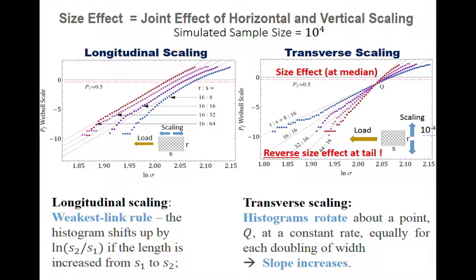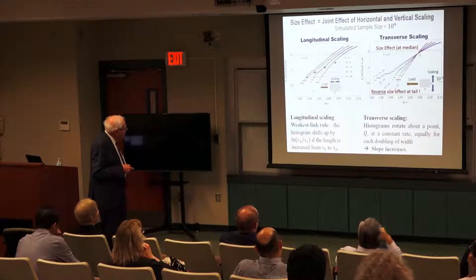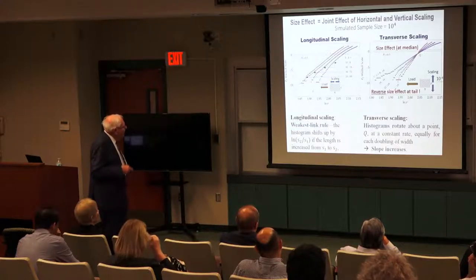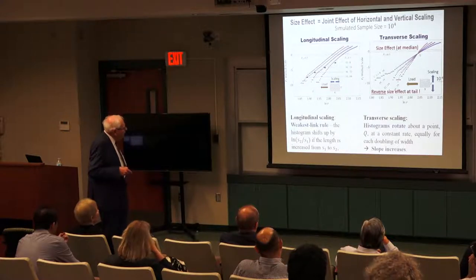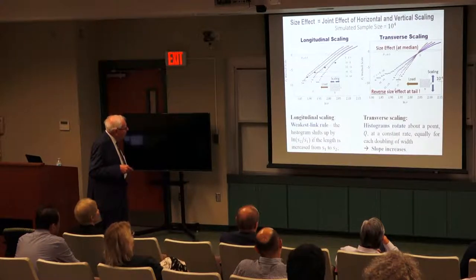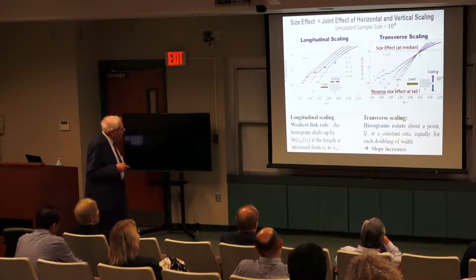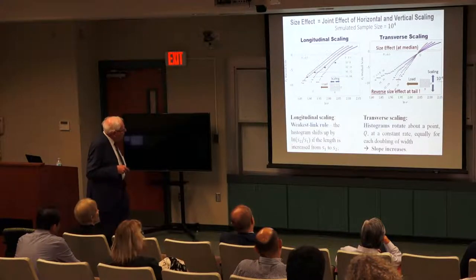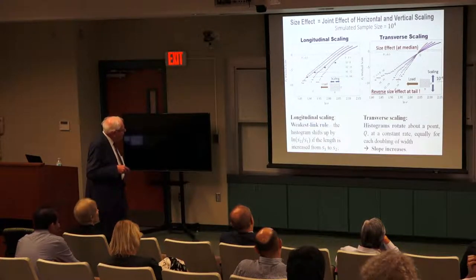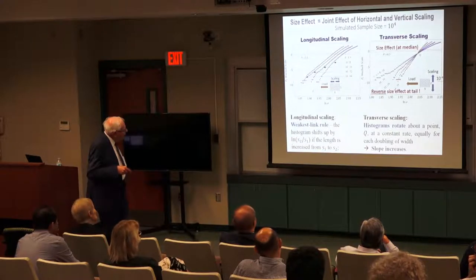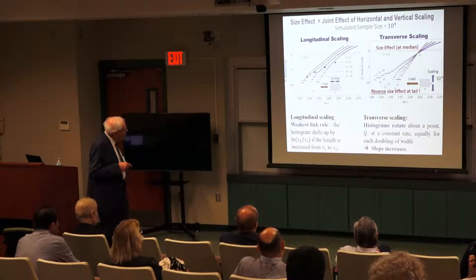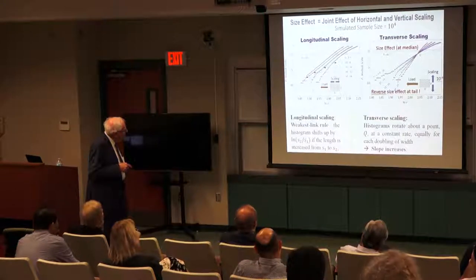And how to determine size effect? Now from size effect you can go back to distribution. Now we found this very simple property. It is difficult to judge what happens if you enlarge geometrically the fishnet, enlarge both lengths and widths in the same proportion, which is the definition of size effect. But we split it into two kinds: we enlarge it longitudinally and here enlarge it laterally.